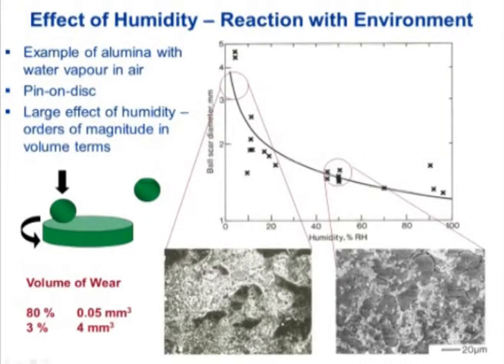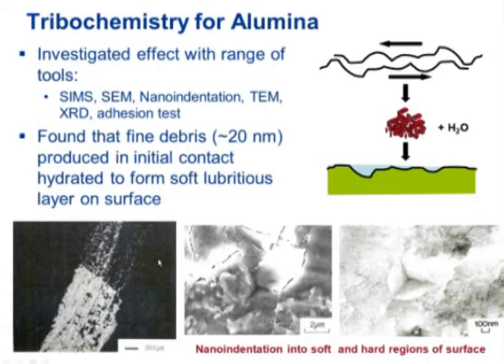You might say, oh, ceramics, we all know that there's an effect with water on ceramics. Oh, and this is more stuff on the mechanism. I forgot that this slide was here, to be honest. This shows a little bit more about the mechanism. It's wear debris that reacts with the water to form this softer phase that fills in the gaps in the hard surface. And you can see a micrograph.